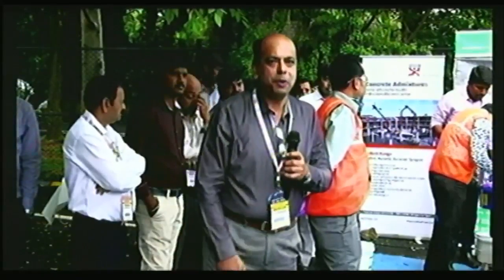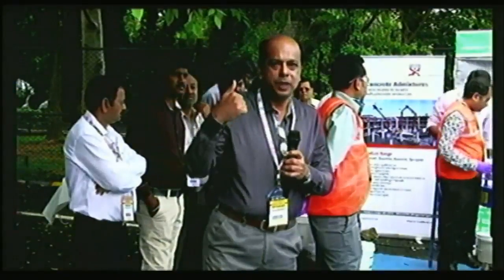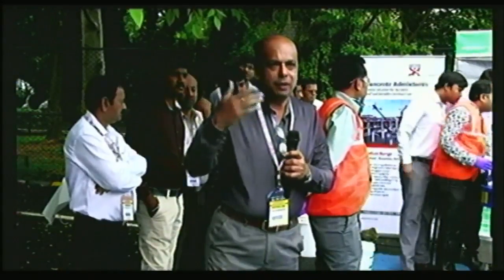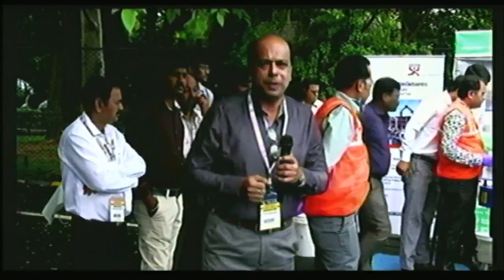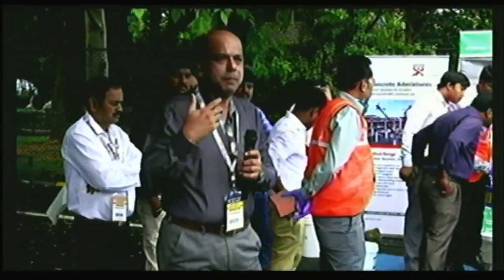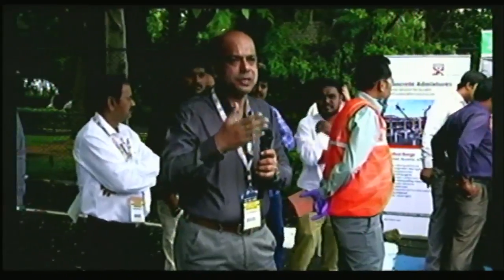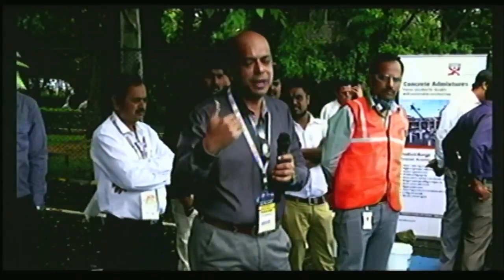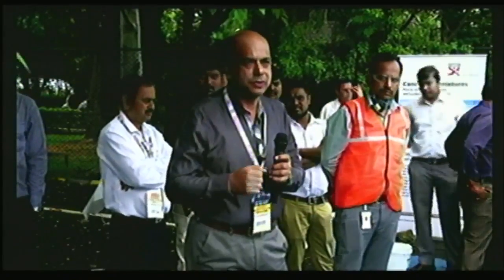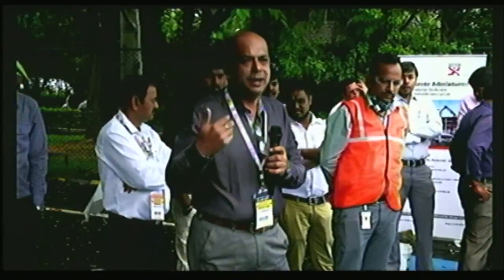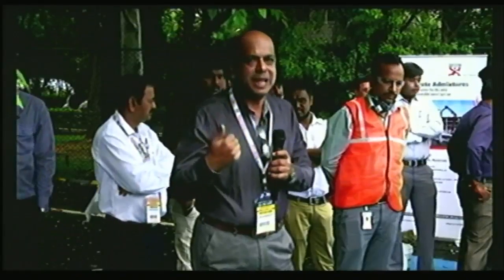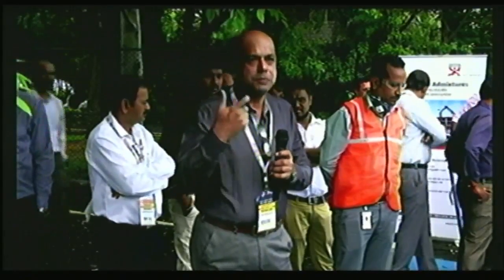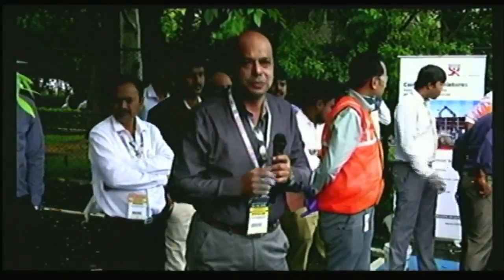One more important point I'd like to mention is the strength parameter gain. Normally when we go for high volume replacement of GGBFS, we have an apprehension that the strength gain at 7 days and 28 days is going to be lesser. But here the scenario is slightly different. It is going at par with any 50-50 replacement with OPC and GGBFS. The reason is only one thing. I had a discussion with Manjunath on this subject. The fineness of the GGBFS has been increased from 350 to 380. This fineness is playing a very important role.